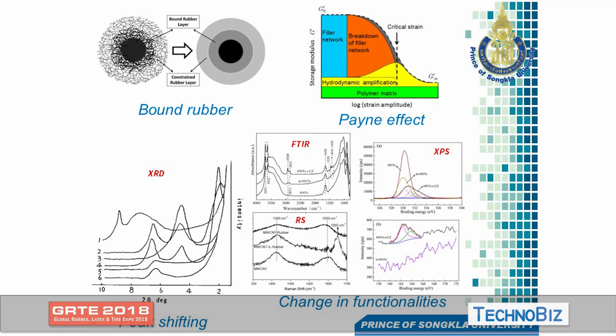So in the case of organoclay, they use this kind of technique to confirm whether there is intercalation between two different stacks of layers. If there is a peak shifting to smaller angles, it means that there is intercalation of the rubber inside the clay laminations.